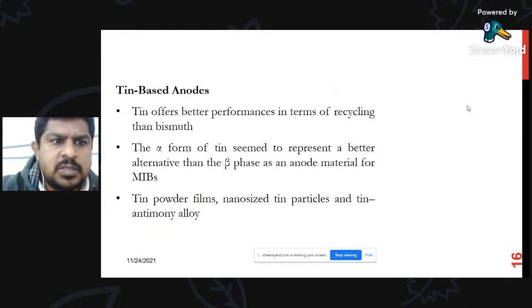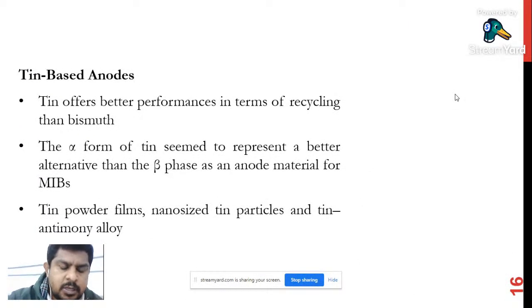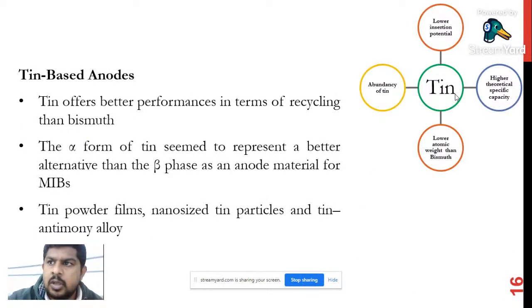Next one is the tin based anodes. First was bismuth, which is an alloy, and this is also an alloy compound. In tin based, there are some good advantages when you compare with bismuth. The first one is the atomic weight of tin. Tin is lower when you compare with bismuth. If the atomic weight is lower, then the weight of the battery also changes. The next one is the recycling.